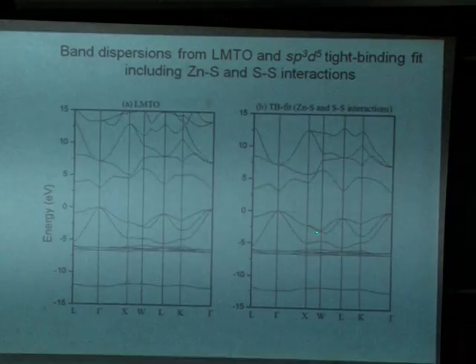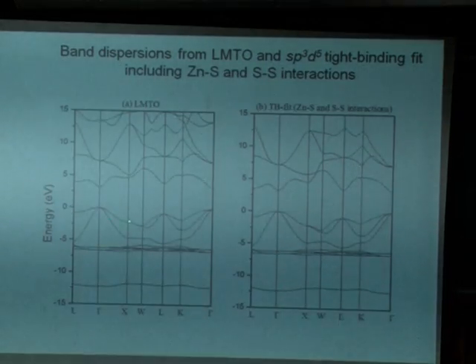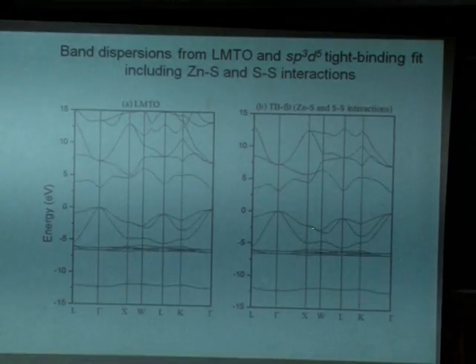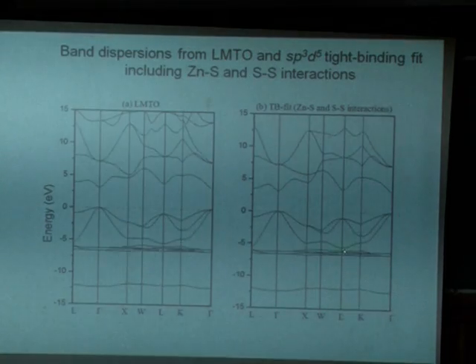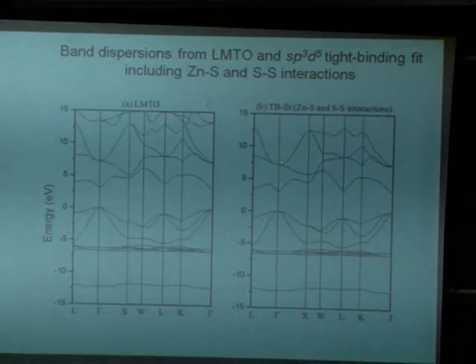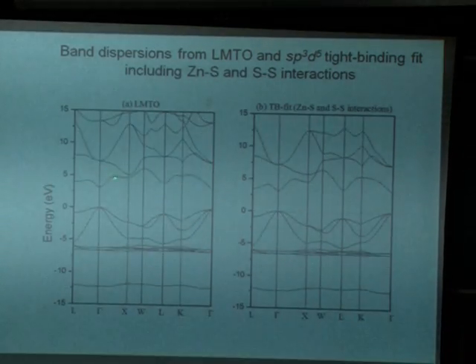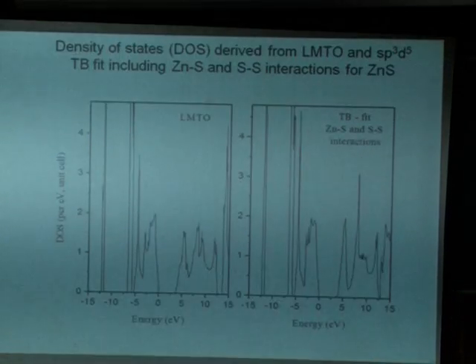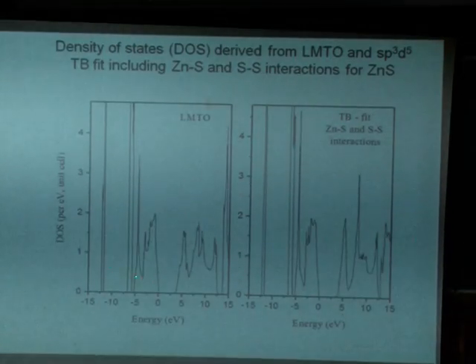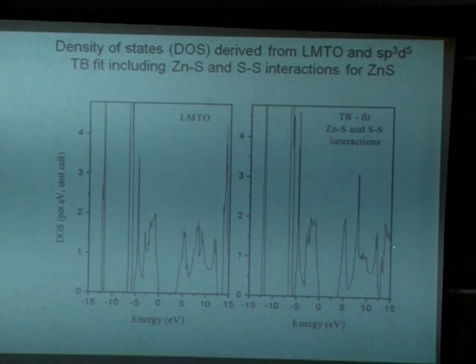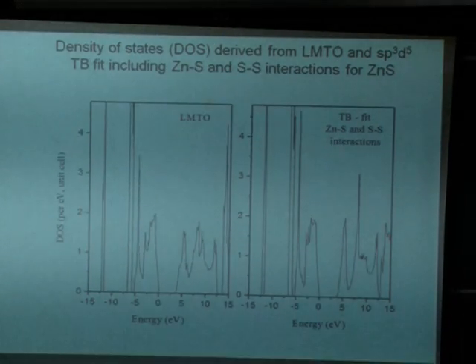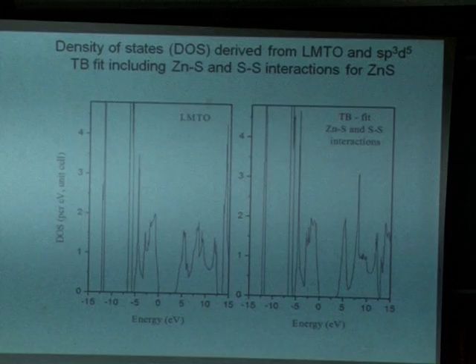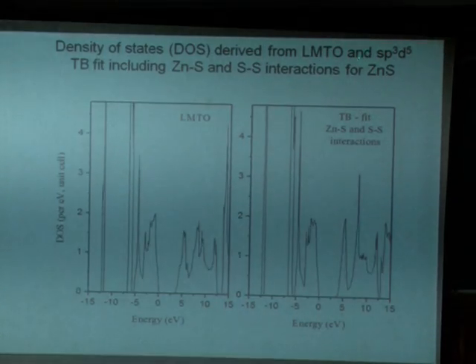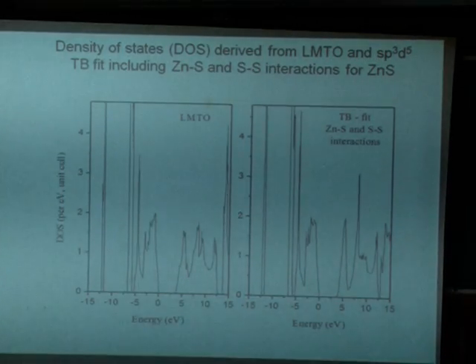And now you see that this becomes nearly degenerate, like over here, which was a very big gap. Then this part comes out, it's no more flat. This part begins to get a dip, not as much, but quite good. So essentially, this is the density of states from the truth, and this is the density of states from this tight binding model. So now we have got the model that you are happy with. That is the way we build up the tight binding model.